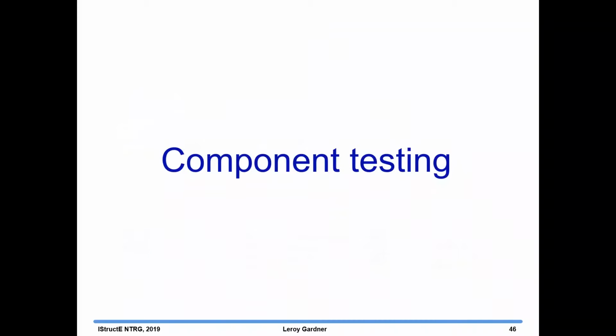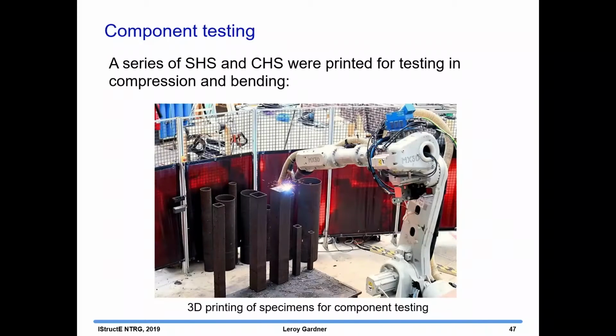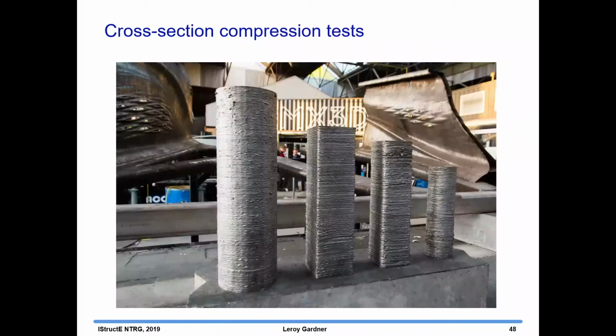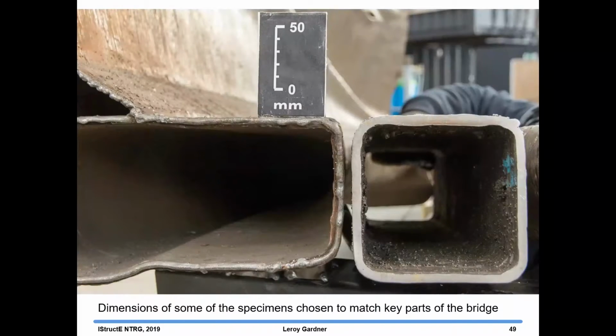Okay, so that's the material properties. We then looked at bits of the bridge, so component testing. We printed a series of square and circular hollow sections for testing in initially compression, and we still have some bending tests to do. So these are the specimens having been machined flat on the ends and cleaned. And the specimens were chosen to match key parts of the bridge, so at the base and at the top of the handrail.